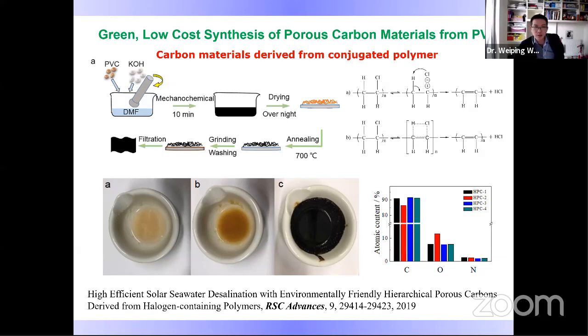So I used PVC with KOH and DMF, mixed using mechanical grinding, and the color changed from transparent to yellowish to brown or blackish, indicating the formation of conjugated bonds inside this polymeric structure and the reaction of chlorine atoms with KOH to form KCl and water. After high temperature processing, we can get pure carbon materials without chlorine atoms. They only contain carbon, oxygen, and nitrogen.